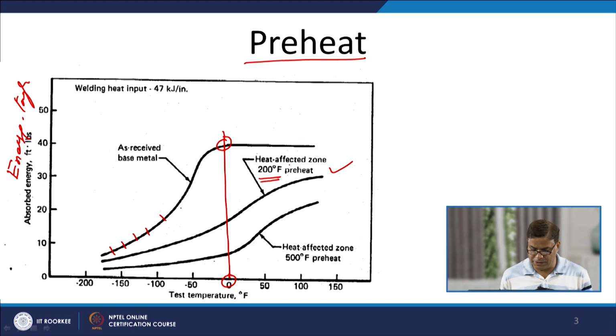preheating of 200 Fahrenheit offers somewhat better impact resistance in terms of the energy absorbed as compared to the case when the preheat of 500 Fahrenheit is used. So, what we can see here in all the cases, there is a drop in the energy absorbed with the reduction in temperature, but this kind of drop is more severe when the preheat temperature is high, especially with regard to the impact resistance of the heat affected zone.